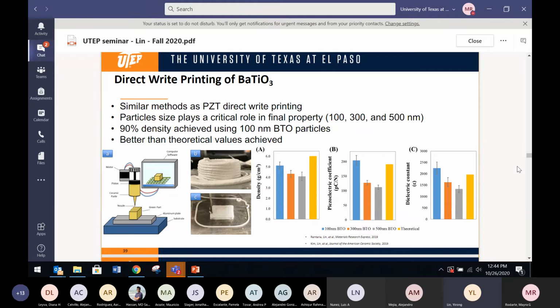So what we find here is this density is a function of particle size. The yellow here is the theoretical value, and blue, orange, and gray are 100, 300, and 500 nanometer particles. So here, what we're seeing is these 100 nanometer ceramic particles give you the best density, the best piezoelectric coupling coefficient, and the best dielectric constant. The reason is because the smaller the particle is in nanometer scale, the higher surface energy you'll have, so the better it'll sinter. This is very interesting to see, because you want to have a high density, so therefore that gives you better mechanical, electrical, and dielectric properties, right? This is exactly what we're seeing here.